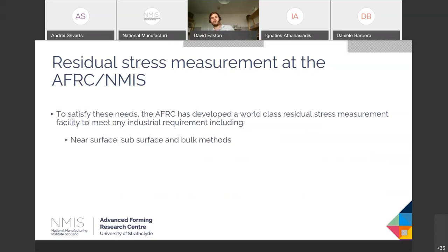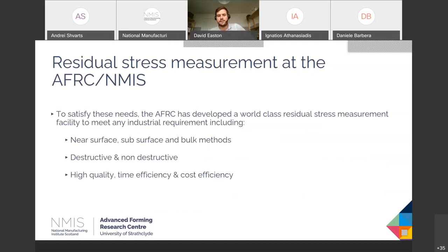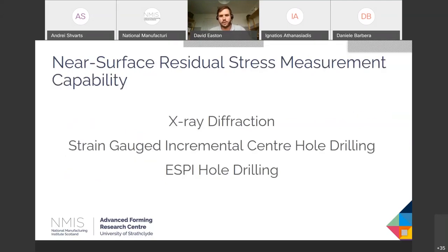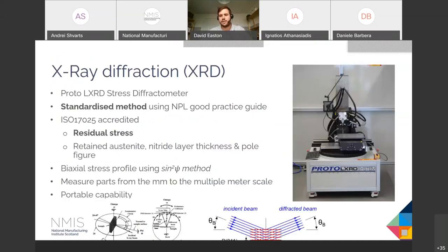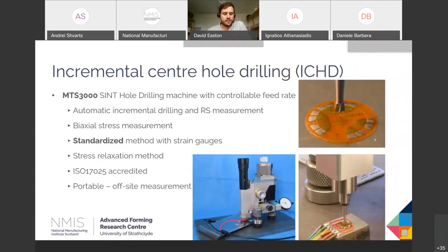To satisfy this, we've developed a whole suite of measurement capabilities, covering the near surface, bulk methods, all sorts of destructive and non-destructive, and measurements that satisfy whether it's quality demands, time demands, or cost demands. On the surface level, we've got X-ray diffraction. So this relies on the interaction of different crystals in the material, and we'll get a spacing between different crystals, and we can measure what that spacing is and how that changes due to strain or residual stress in the part.